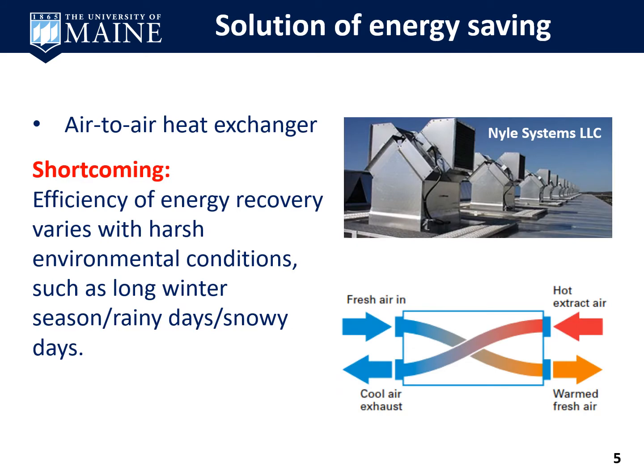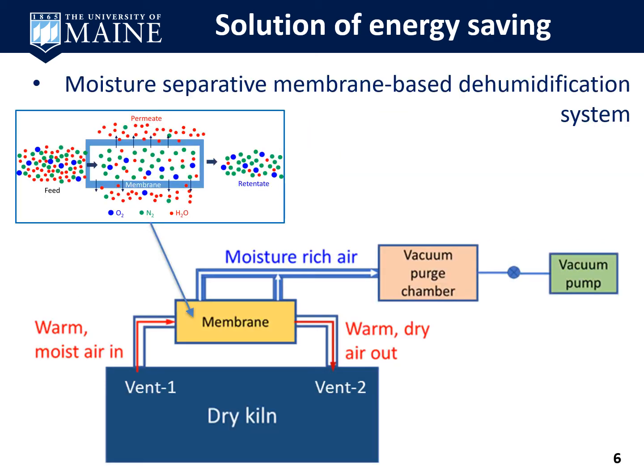An air-to-air heat exchange technique has been applied in some conventional kilns. However, the shortcoming of this heat exchanger is that the energy recovery efficiency could be affected by harsh environmental conditions, for instance, extremely long winter seasons in the northern US and Canada. To solve this challenge, we proposed to develop a hollow fiber membrane-based dehumidification system to dehydrate the exhaust air from the kiln and then send this warm dry air back into the kiln.